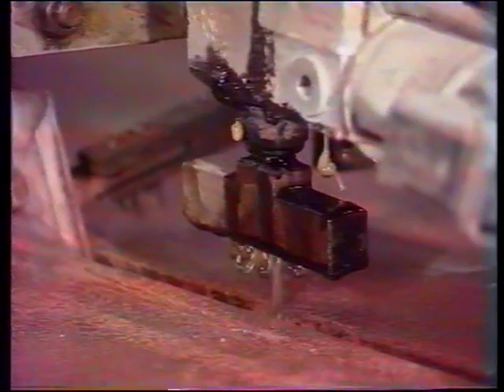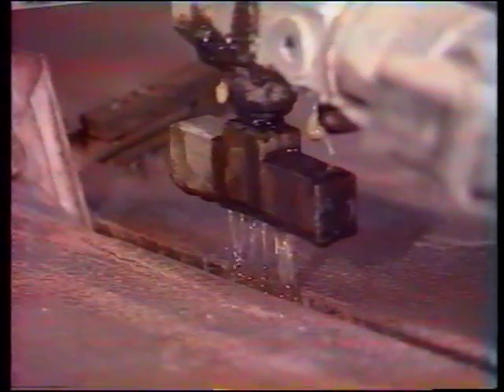Here, wax pegs are being injected at either end of the plate gaps. This protects against edge chipping by restricting any plate movement that occurs in the grinding and polishing operation. Grinding is achieved by feeding a sand and water slurry between rotating cast iron heads and the glass. This starts with a coarse grade of sand at the early heads, then finer and finer grades, to finish with a grade that produces a fine ground surface necessary to pass on to the polishing section.